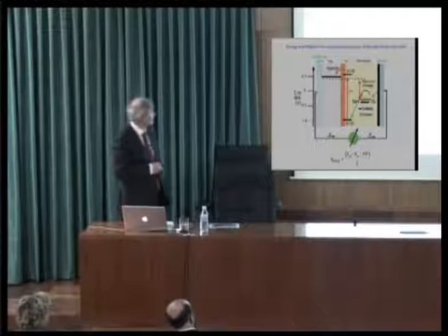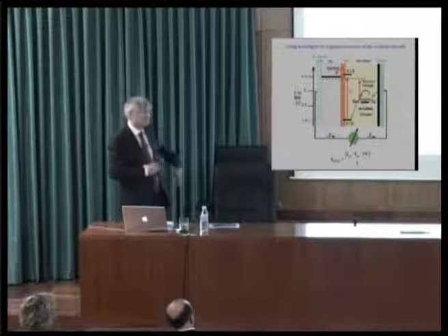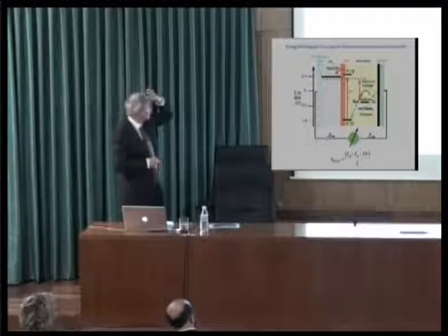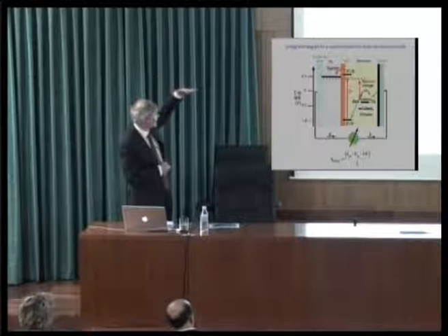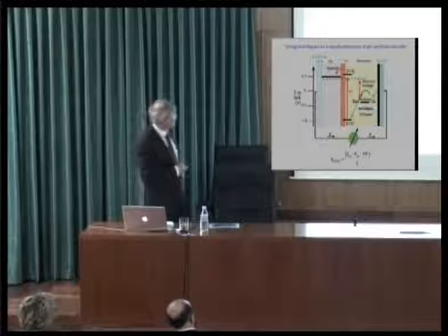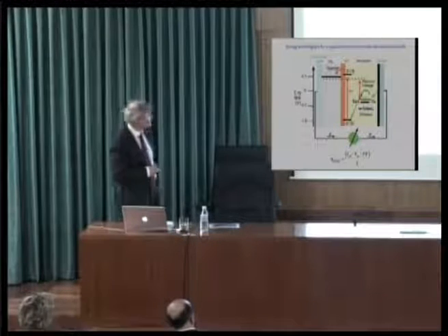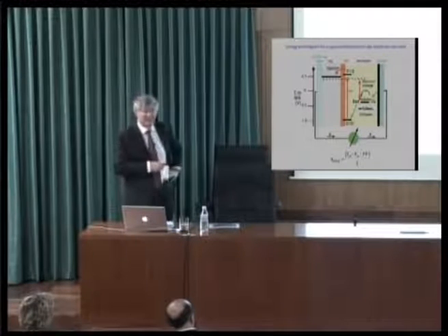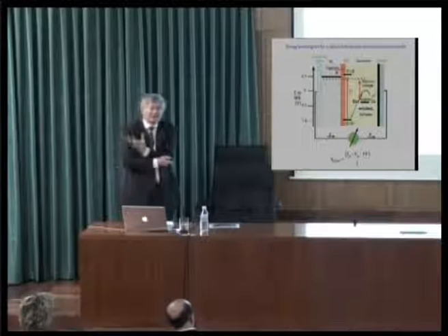And so when you illuminate the cell, the electrons will move the Fermi level higher and higher because you're accumulating electrons. And so that sets one reference. The Fermi level in the TiO2 is one important reference, and the other one is the Fermi level of the solution, or the Nernst potential. So the difference is your voltage, and if you give half of the voltage away, that's not good. It's not exactly half, but